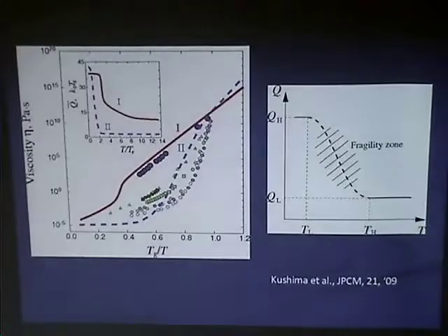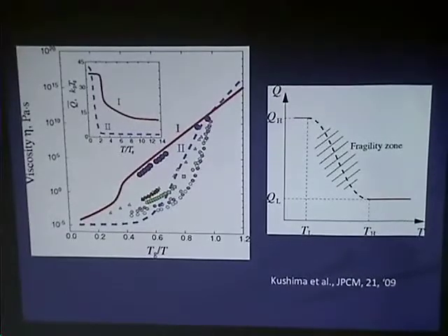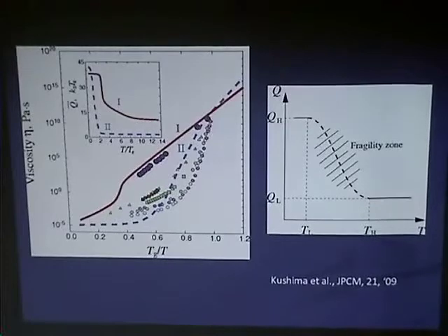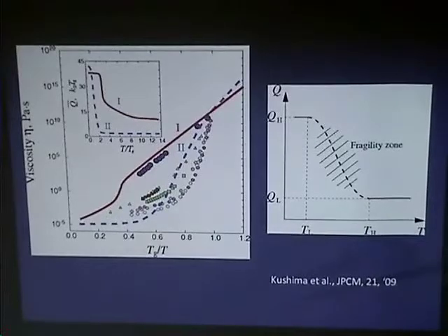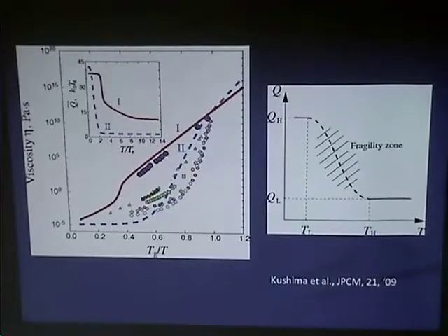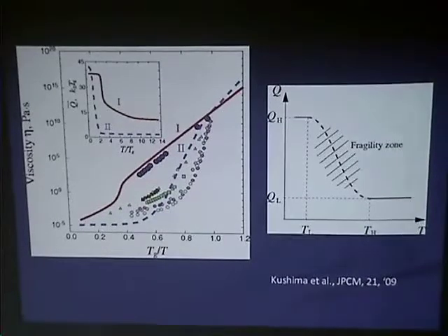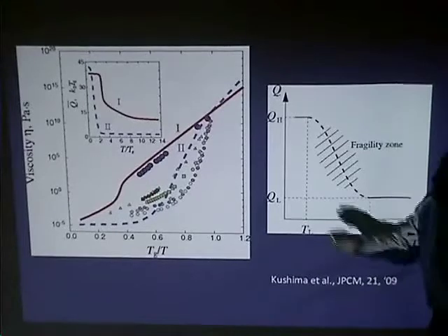steepest descent quench from a higher temperature, you fall into various basins. And those basins, they're shallow. As you do your steepest descent quench to a lower energy, you can fall into some very, very low, but nothing's infinitely low, so there is a low bend over here. This low bending over here is precisely that.